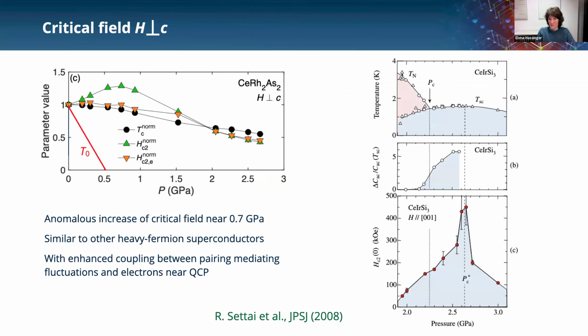So what you see is that in zero field, the magnetic phase usually stops and you cannot follow it inside the superconducting state. But if you apply field to suppress superconductivity, you can follow this line, and then you find that the upper critical field peaks roughly at the pressure where this line goes when superconductivity is suppressed. And that's what we see in our material. So here is normalized T0, normalized critical field, and this peak is very close to the quantum critical pressure.